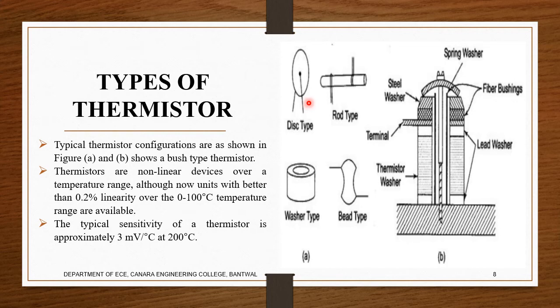They are 1.25 to 25 millimeter in diameter and 0.25 to 0.75 millimeter thick, having a resistance value of 1 ohm to 1 mega ohm. They are sintered and coated with silver on two flat surfaces. On either side, we have the flat surfaces which have been sintered using a silver material.